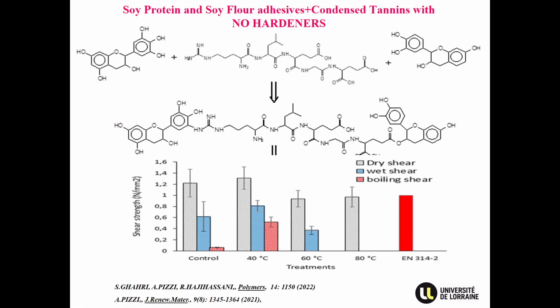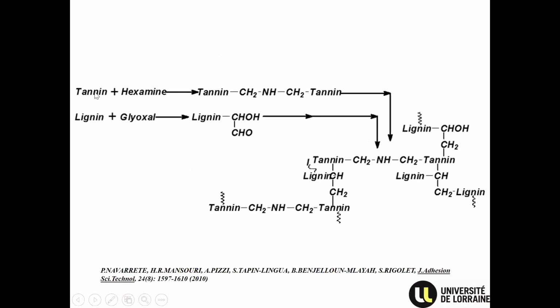We propose this as a concept, more than a formula, because you can superpose the system on a lot of other systems used today. Then you can have a mixed tannin-lignin, pre-glyoxylated lignin, tannin and hexamine, and you will have mixed cross-linked polymers of this type. That also works quite well, but you have to pre-glyoxylate the lignin, and you're still using hexamine.